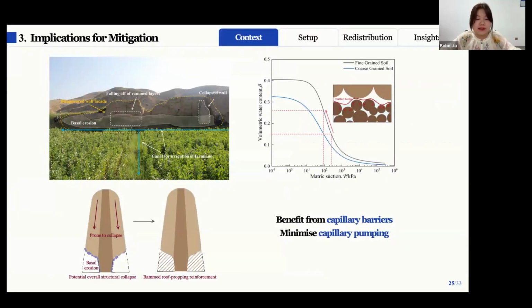So how can we apply this understanding to mitigate the salt damage in earthen sites? The key idea is to regulate water and salt redistribution by modifying the pore structure of repair materials. We can take the Great Wall as an example because in many cases, irrigation water transports salts from the foundation into the wall, accelerating the basal erosion. And to stabilize the structure, rammed repair soils are commonly used.